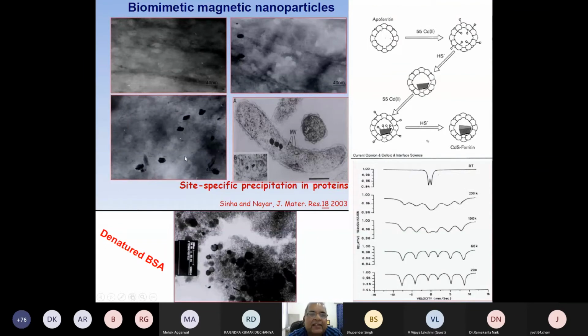So this was very exciting that here in the protein, we could exploit this nano cavity present in the protein structure and could nucleate the nanoparticles of magnetite Fe3O4, which is very similar to what happened in the magnetotactic bacteria. This is a picture from literature where they are showing that the nucleation of the magnetite nanoparticle in the bacteria takes place in the same way as we are seeing in our sample. So this was our second success in mimicking the biomineralization.